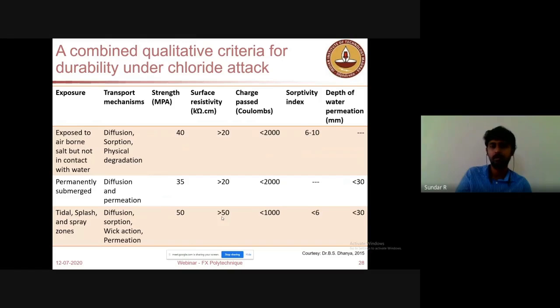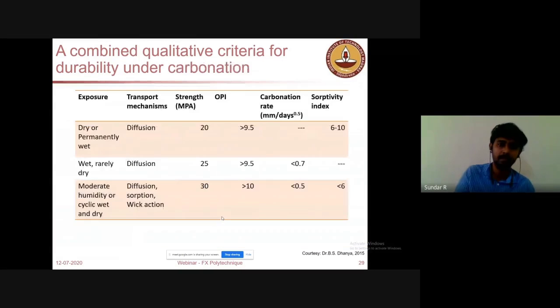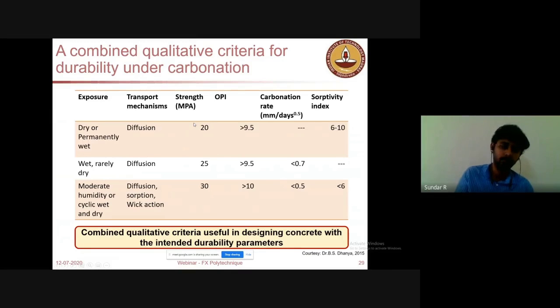So when you go to a site as an inspector, you should have an idea about these numbers which will be present in the codes, which are primarily based on performance-based specifications. These numbers will help you to decide whether to accept or reject the concrete at the site for deciding the quality. Similarly for carbonation, there is oxygen permeability index and carbonation rate, which have been used as a measure to determine the durability, in addition to the strength criteria that has been proposed. So for achieving this intended service life, we should have these kinds of qualitative criteria for durability.